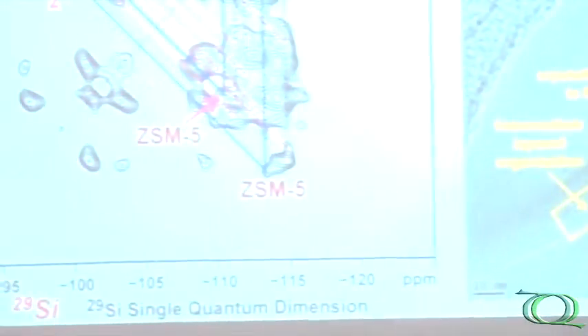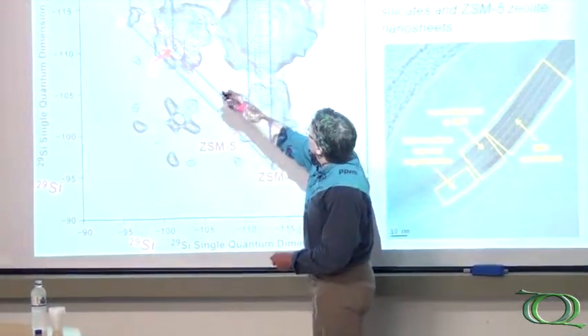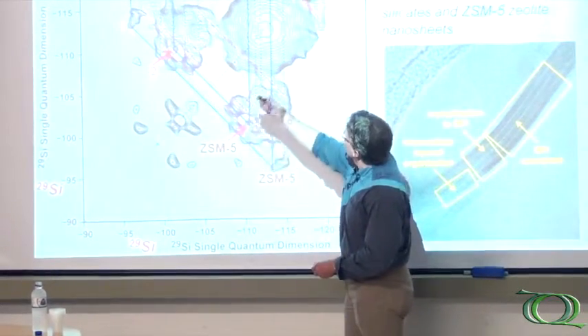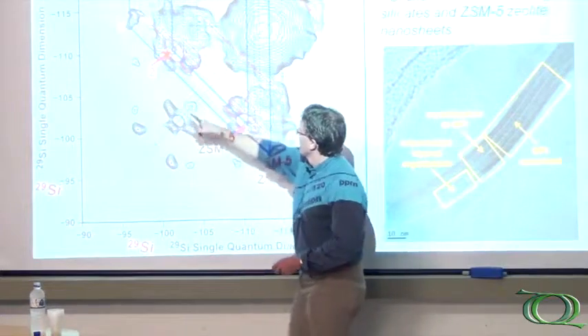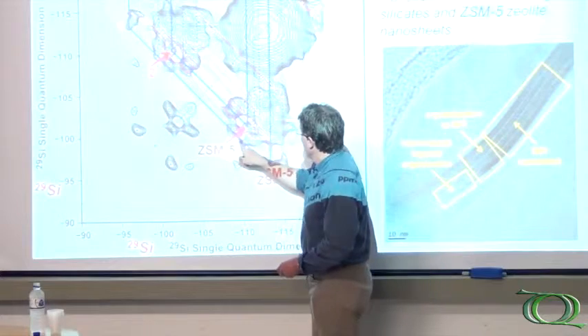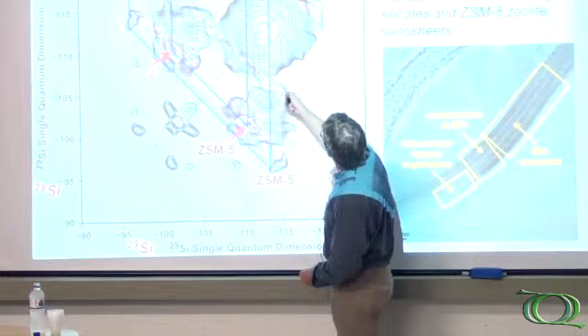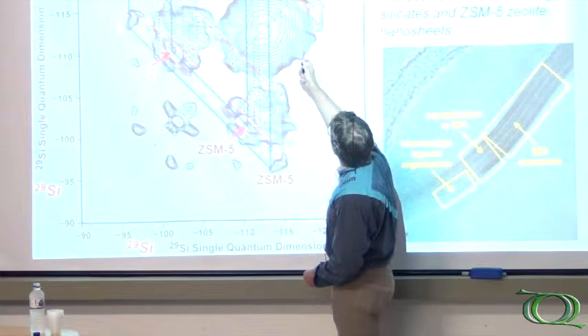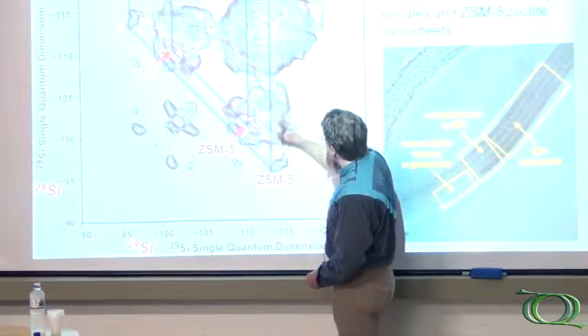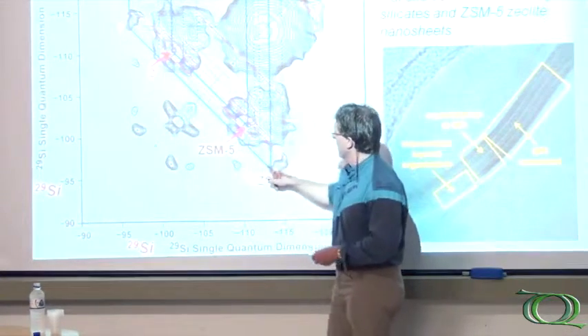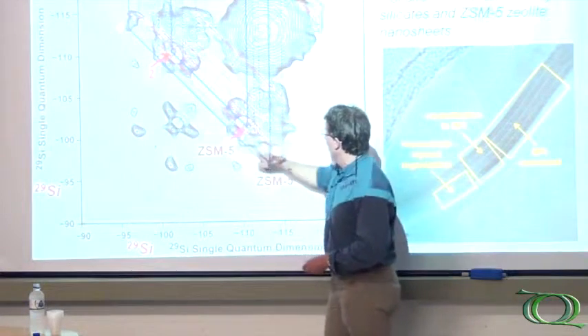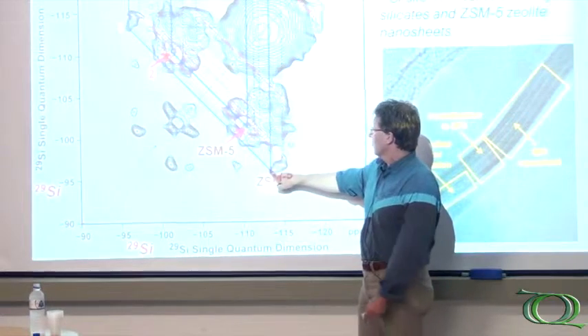If we now look at the next one, and this is the proof that the layered silicate transforms. These are sites one and sites two. I've just drawn a couple of them here. Site one, if we follow this correlation down to this one, this is right in the middle unambiguously of the crystallizing structure. It's not the layered five, not site four. And this one follows right down here. And so this is essentially the smoking gun, the evidence that site one is in the process of forming a bond that will eventually be found as crystalline ZSM5.